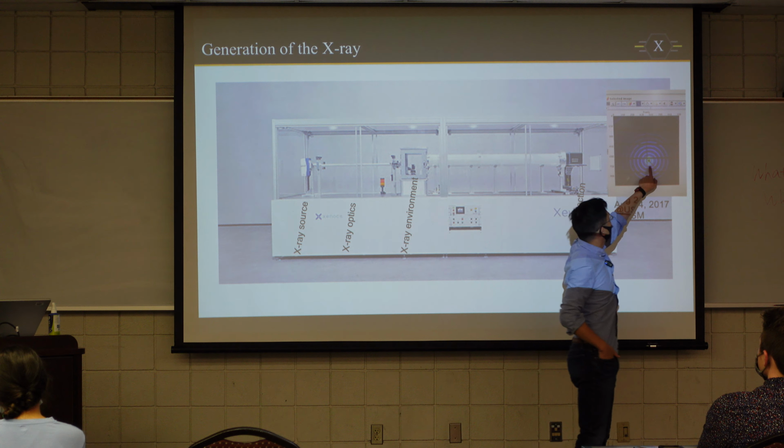Our tool has a lower limit of looking at Q down to about 0.02 or 0.03. That's about this range, when we move the SDD to about 3.8 meter, which is the longest distance we commonly use. In our lab, we can move to 6.4 meter, but we rarely use that because our beam is not that pure and diverges a bit.